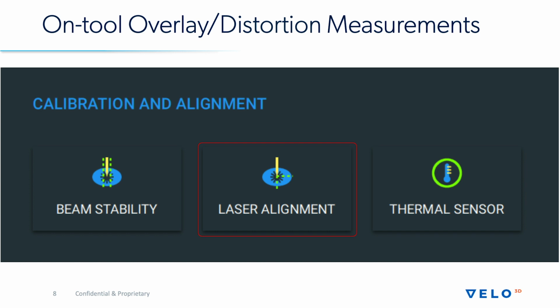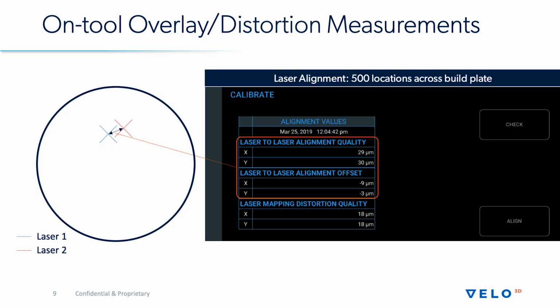So what happens when you click this button is that it actually does a pre-described routine over the entire build plate, and it measures at 500 different spots on the build plate exactly how far off the two lasers are relative to each other. And you can see an example there on the left-hand side where you're basically firing a pattern with the two different lasers and then using the sensors on the system to measure how far off they are. The average distance between the two lasers is given by the alignment offset there. In this case, it's about 8 micron error between the two lasers. And then the standard deviation of all of the errors all over the build plate is given by the laser alignment quality, in this case about 30 microns.